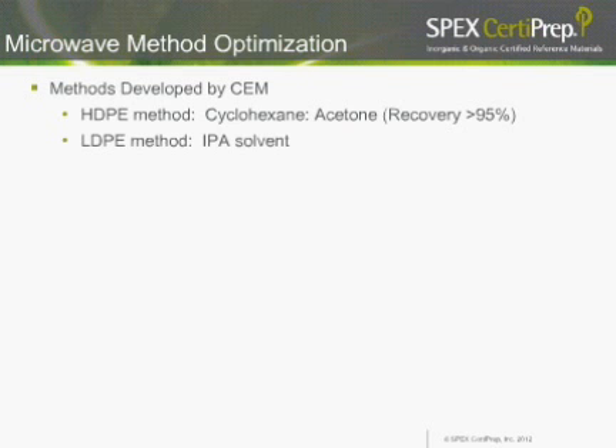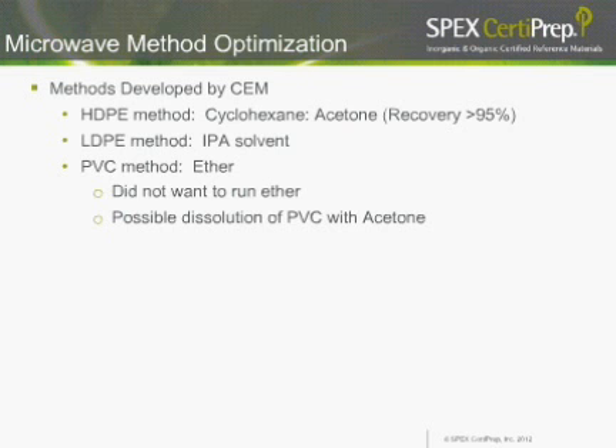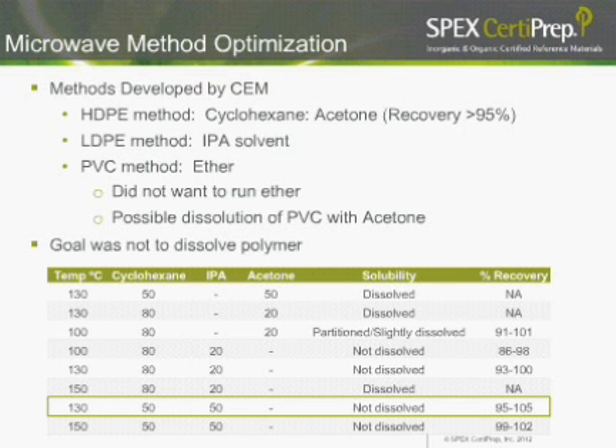When looking at some of the other methods, we looked at an LDPE method. That is an IPA solvent base, again with a very good high recovery. And then we had a PVC method written by CEM, which prescribes an ether as an extraction matrix. We decided we didn't want to run ether, so we looked for an alternate matrix. We also started looking back to the other methods we had just run, and we had the choices of cyclohexane, acetone, and IPA. We did not want to run the acetone because we were afraid the acetone would totally dissolve the PVC, and it would kind of defeat our goal, which was not to dissolve the polymer.